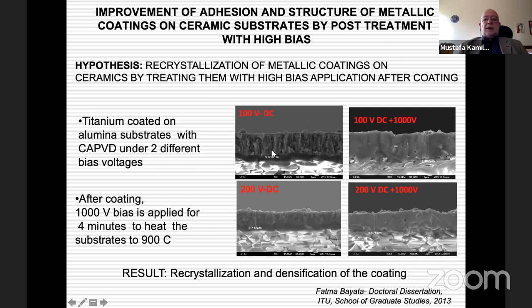So here you see the structure of the coatings that we have produced by using only a bias voltage of 100 volts, and this is 200 volts. So here you see the typical columnar structures of the titanium PVD coated materials. So this structure was not very valuable for us. So we wanted to convert it into a denser structure by recrystallization. So what we did is we applied a 1000-volt bias after this application to heat the substrate to 900 degrees. Because these coatings are very thin, 4 minutes of application of this bias voltage led to the increase of the substrate surface to 900 degrees, leading to densification of the coating. And this helped us a lot in further utilization of the structures for sensor applications.